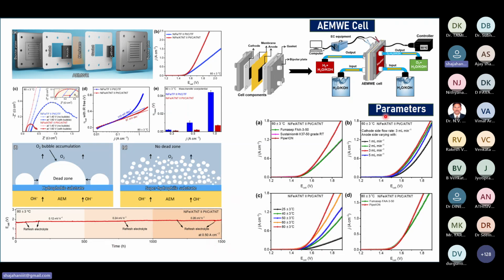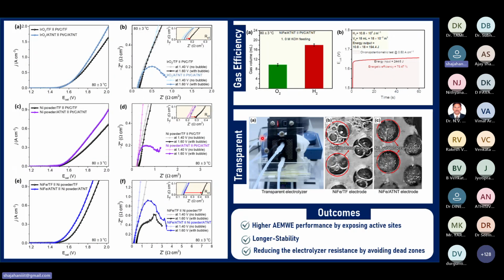We also studied parameters using different membrane based setups, different flow rates and different temperatures, and we optimized it by varying these parameters. We observed that Piperion at 3 ml at 80 degrees shows better performance than the remaining membranes. All these experiments were done using KOH solution. The same experiments we also carried out using commercial catalysts, and we observed the same results. This is not so important, because we observed the same trend on the ATNT based substrate with different catalysts.